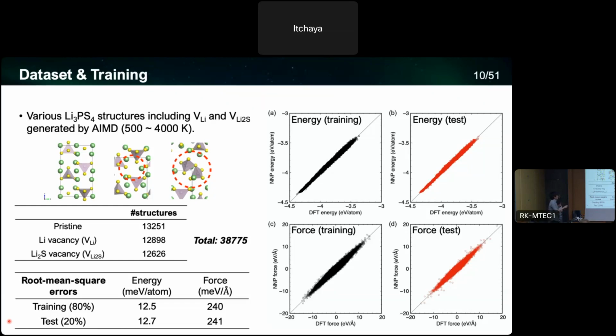And in addition to the pristine or stoichiometric case, we also introduced some vacancies, like lithium vacancy or Li2S vacancy. And these are the numbers of structures that I used for making the neural network potential. But finally, we used around 40,000 structures. The table at the left bottom shows the root mean square errors of the neural network potential, which are basically around 12 or 13 millielectron volt per atom for energy, and around 200 or 300 millielectron volt per angstrom for force. And these are the parity plots for energy and forces. The black ones are the training, and the red ones are the test data.